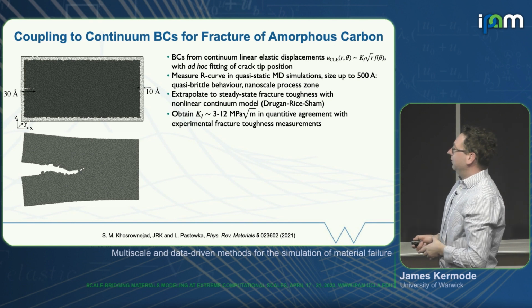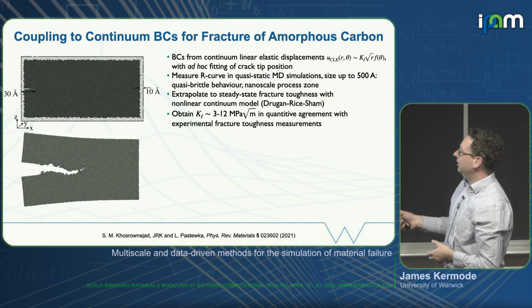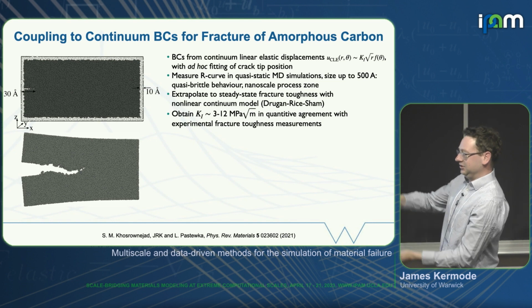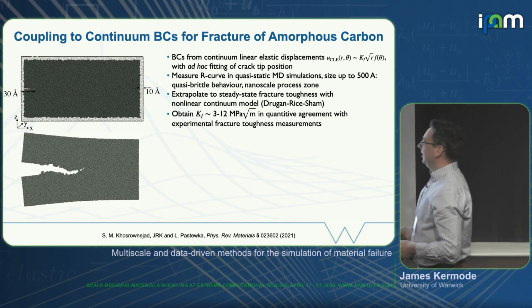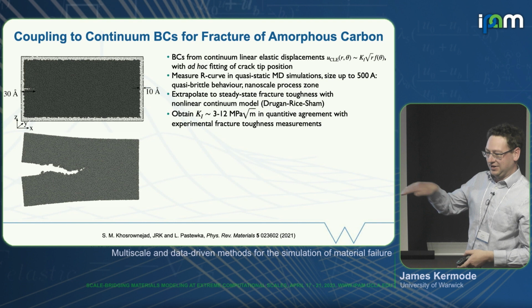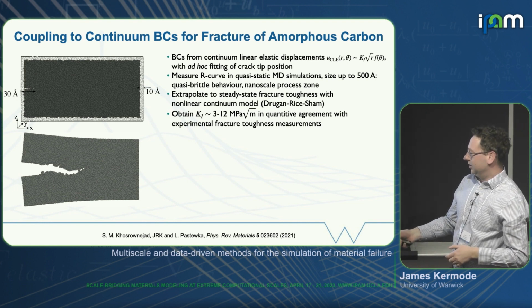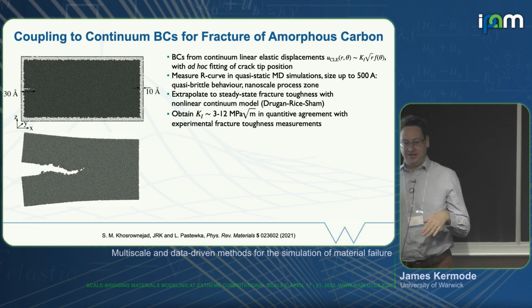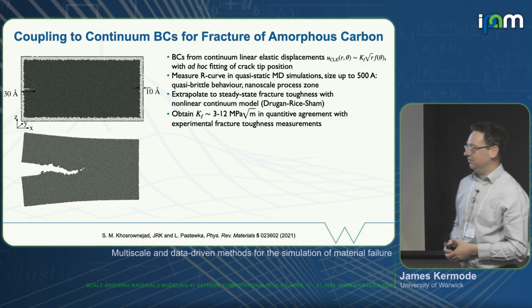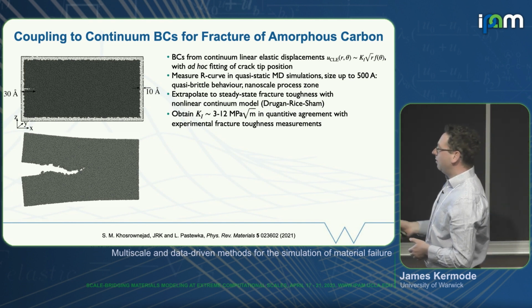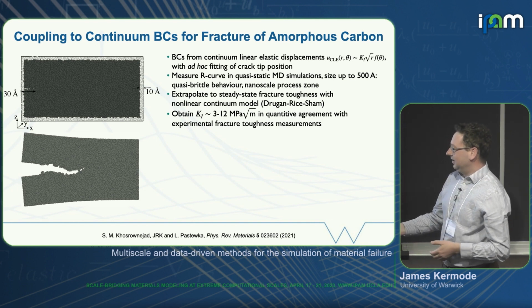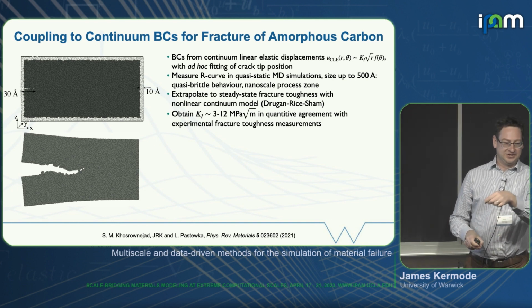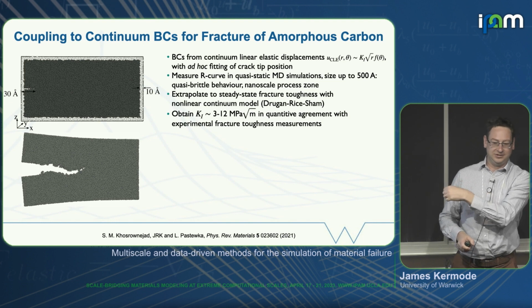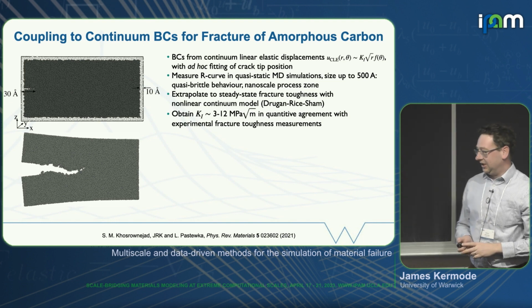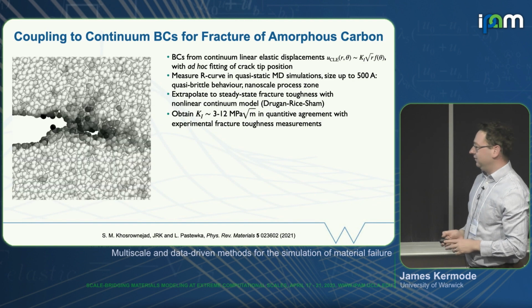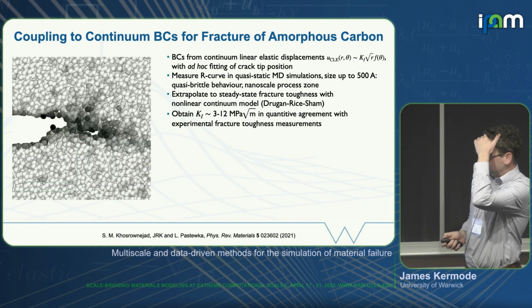So this was fracture of amorphous carbon. We have a giant piece of amorphous carbon. We apply a continuum linear elastic boundary condition to the specimen, and as the crack advances, you can see it wiggles around in quite a complicated way because it's not a crystal anymore. There isn't a cleavage plane, and so it's a more complex response. And what we had to do in this case is fit the crack position as we observe these dynamics and move the center of the continuum field in a bit of an ad hoc way. And that was a little bit unsatisfactory, but actually in terms of practical outputs, it was quite useful.